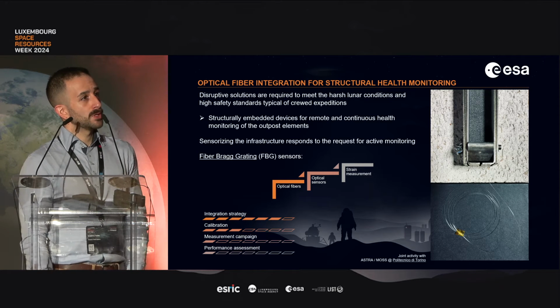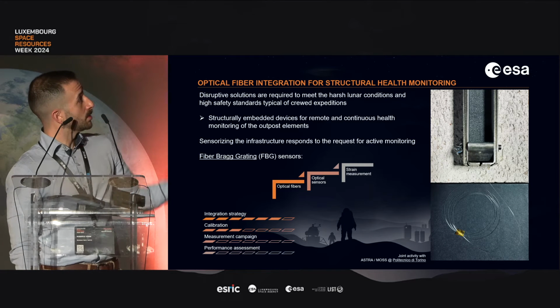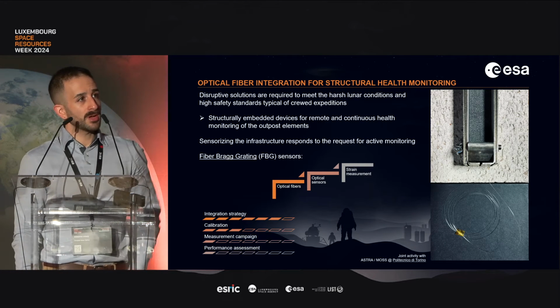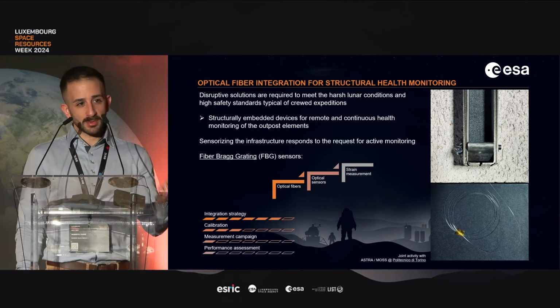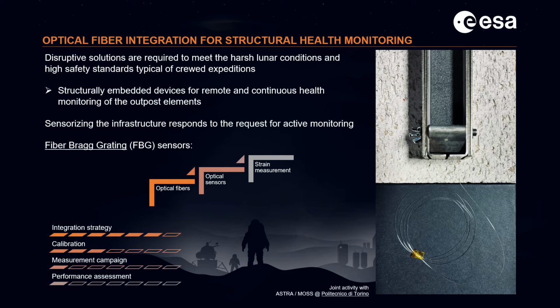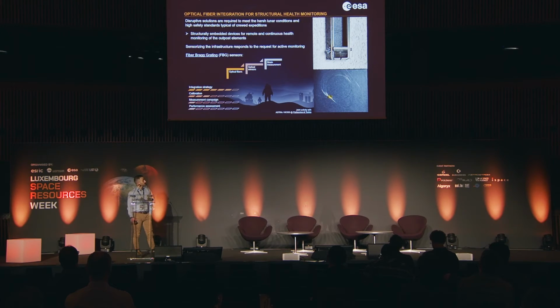So we developed a process to integrate these fibers into the brick. You see the picture on the right. The fiber is somewhat visible, but you can imagine it's transparent and very thin. And the fiber is inside of the brick. It was cured within the brick, so it's integrated with it. Our technology is really suitable for doing this because the temperatures are not that high, so the coating of the fiber can survive, and also the compaction pressures that we apply are not that high. Processes that need higher compaction pressure wouldn't be suitable for this solution because of the high shear strengths that would be developed across the fiber.